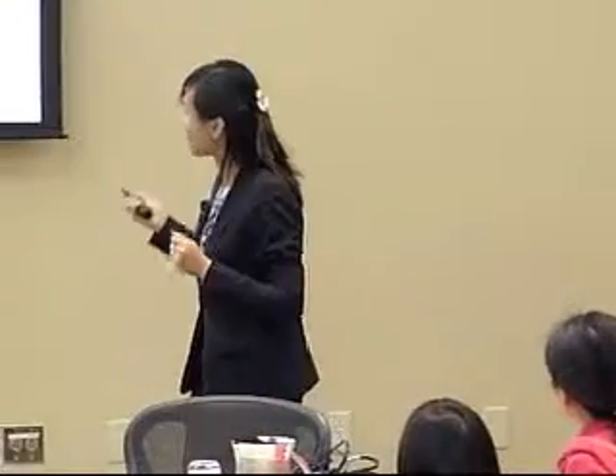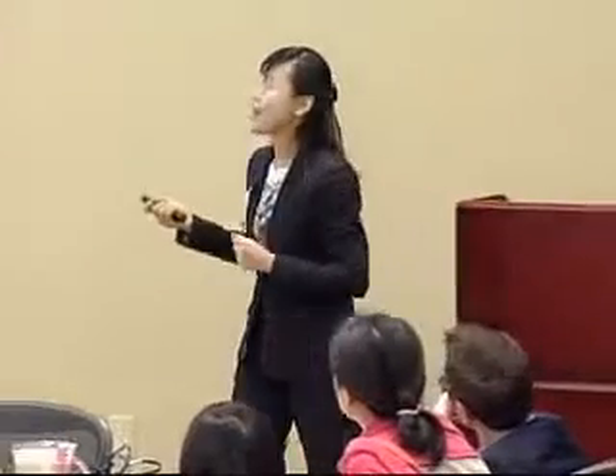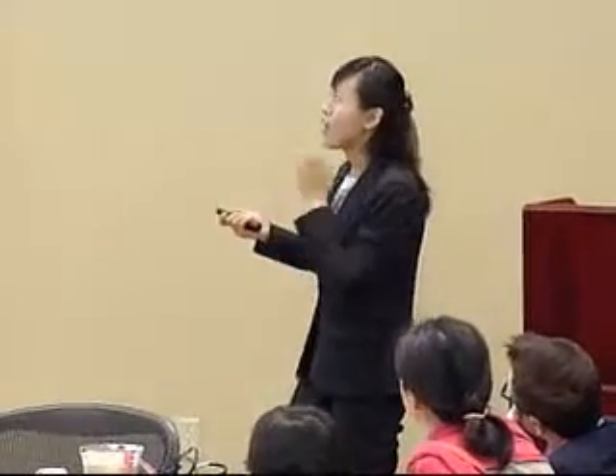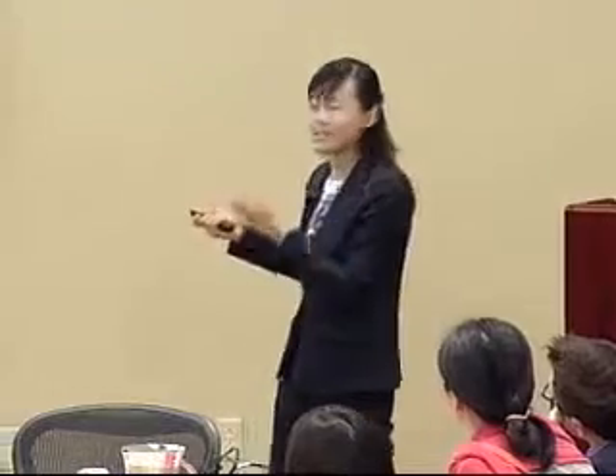In terms of silicon oxides, nitrides, that's another family. That's very brittle, very fragile materials. And in this case, they fracture by very sharp, very clean cleavage cracks. And this kind of brittle fracture, the polymer substrate actually does very little to prevent that. And their failure strain is very, very small, only 1%.